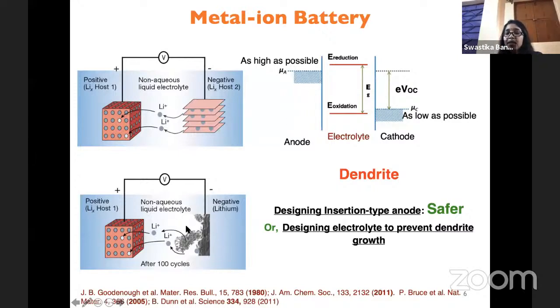So in reality, what happens is, if we use lithium metal as the anode, we have many unwanted electrochemical reactions. At the same time, it also happens at the cathode side. There are electrochemical reactions and chemical reactions at the interfaces. So if we use the lithium metal anode, we can achieve the maximum possible capacity depending on how much energy you can store. But you have a lot of other difficulties, like the safety issue and the stability issue. So designing an insertion type anode other than the pure lithium metal anode could be a safer option to avoid such reactions at the interface and the dendrite formation.